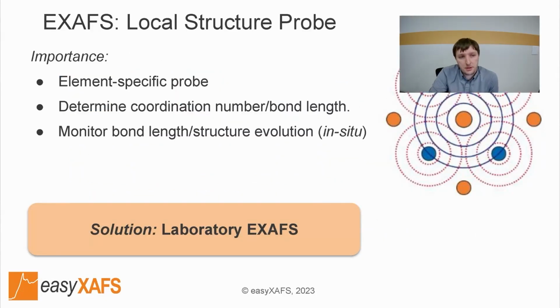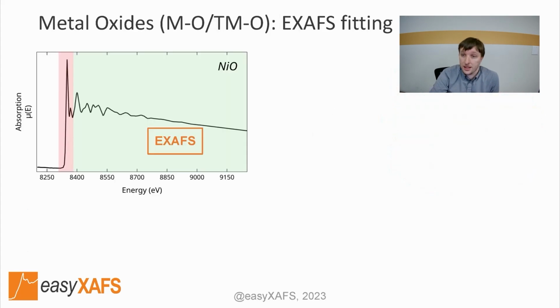In addition to the chemical and oxidation state sensitivity, the EXAFS portion of this technique can be used as a local structure probe of the element of interest. With structural models, a wide range of information can be gained about the coordination environment and bond distances. In particular, the XAFS spectra is often tracked in in situ and operando setups to directly monitor the evolution of the local structure. Looking at this in practice, we see the typical oscillations for a nickel oxide reference pellet.